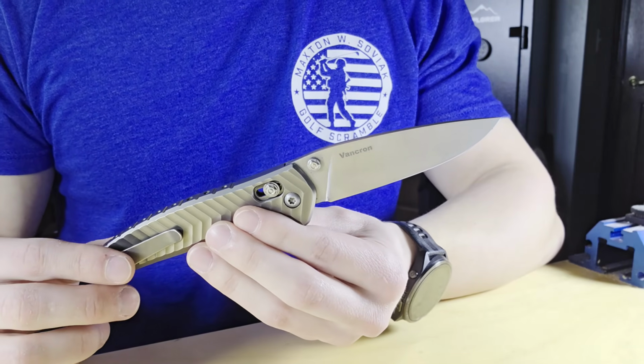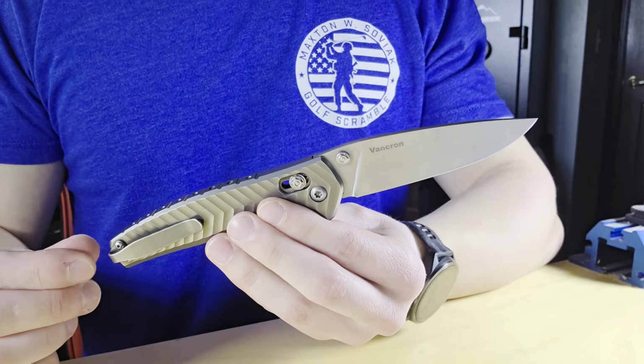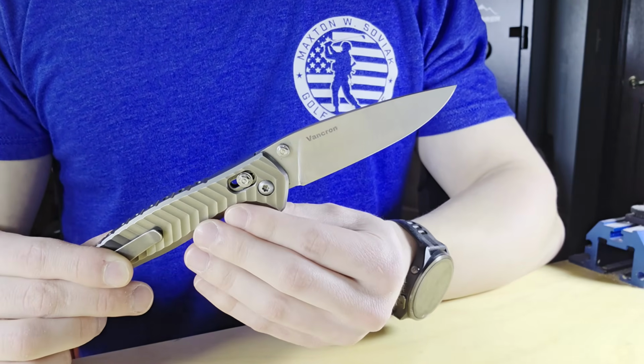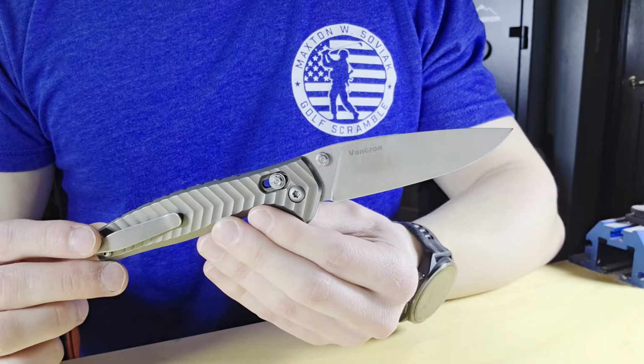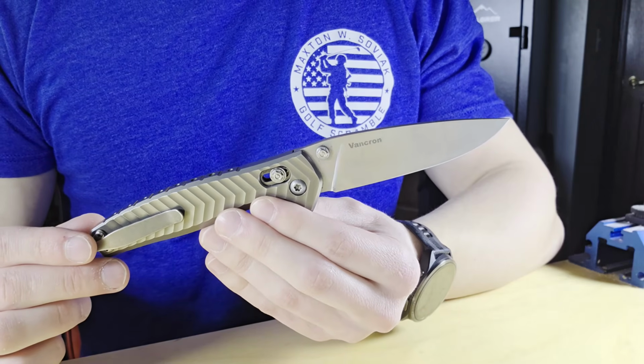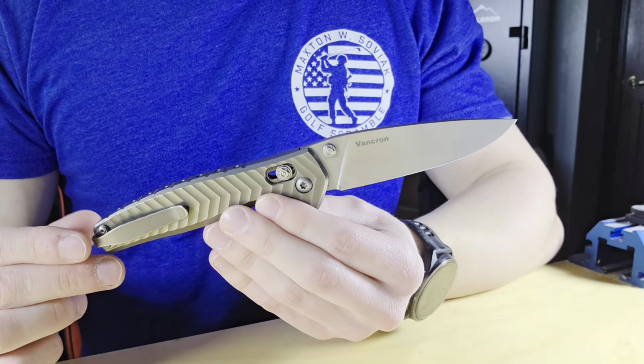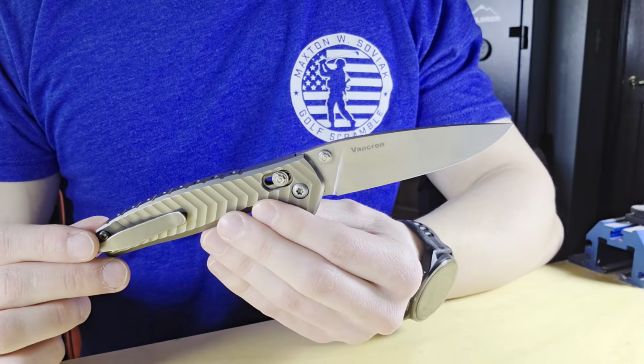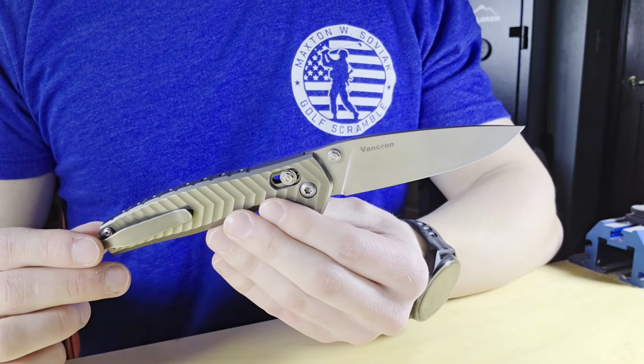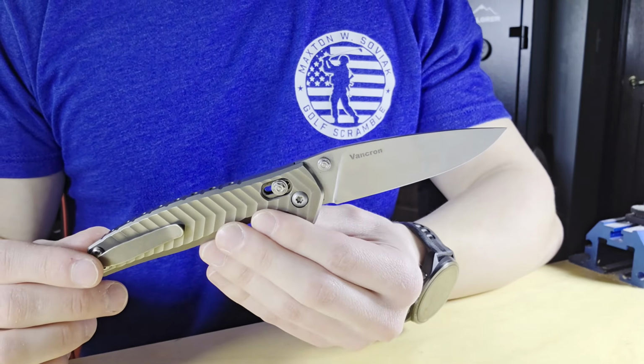Sometimes you have super hard steels like Maxamet that can be a little bit temperamental with burr formation and wanting to break off. And that makes sharpening overall a bit slower because you have to be more careful forming a burr and removing it. But this didn't really have that issue at all. It formed a burr very, very fast, and I never had any issues with deburring it. It was a dream to sharpen.